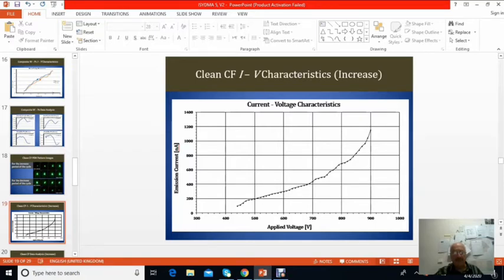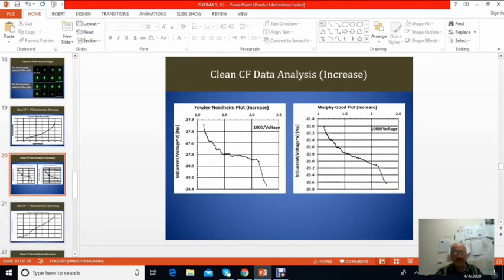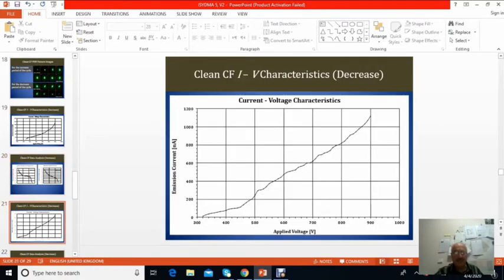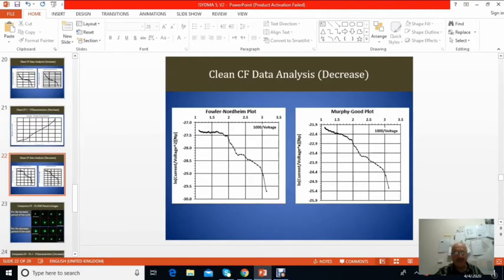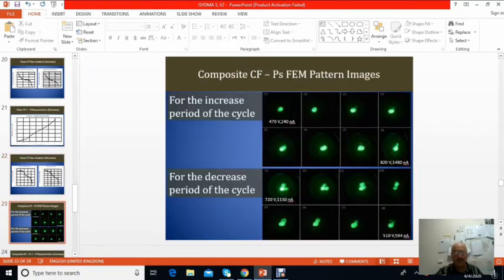So we go down to the clean carbon fiber. So now we finished with the metal, now with the clean carbon fiber. This is the IV characteristics of the standard carbon fiber field emission tip, and this is the Fowler-Nordheim plot, and this is the Murphy-Good plot, for both cycles. This is the decrease, and then this is the clean carbon fiber analysis for the decrease. This is the Fowler-Nordheim plot, and this is the Murphy-Good plot.